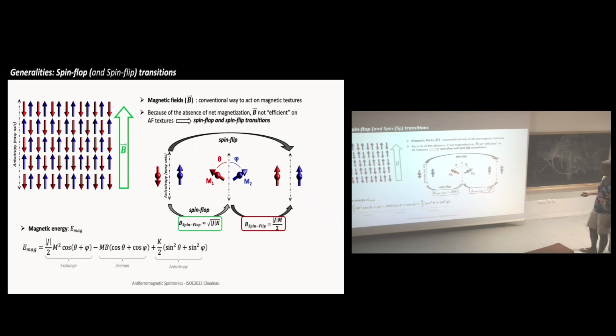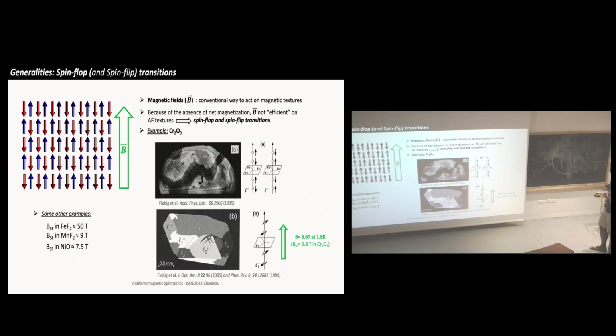And then you have another transition. Most of the time, we call this the spin flip. This time is when we want to fully align the two spins. And this one scales with the exchange times the magnetic moment. But if you put in some numbers, if you take some examples, they are very high. For the spin flip, they are tens of Tesla most of the time. So it's quite difficult to reach in a conventional electromagnet, for example.